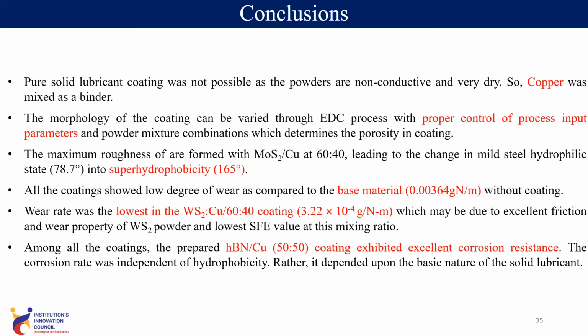Conclusion that we have established: a pure solid lubricant coating was not possible as the powders are non-conductive and very dry. So copper was mixed as a binder to make the green compact tool conductive. Basically, the morphology of the coating can be varied in the EDC process with proper control of input process parameters.